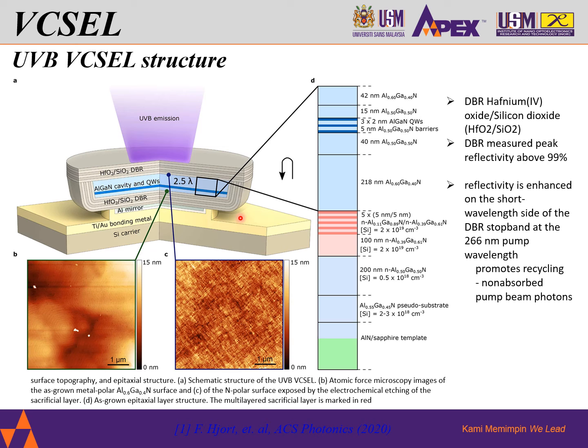The bottom DBR is deposited on the grown epitaxial surface, whereas the top DBR is deposited after the flip chip bonding, and the N-polar aluminum gallium nitride surface exposed by electrochemical etching beforehand. The etched surface here has a root mean square roughness of 1.7 nanometer on a 5 by 5 micrometer squared area, which is similar to the 2.2 nanometer as grown shown here, demonstrating the capability of the electrochemical etching to